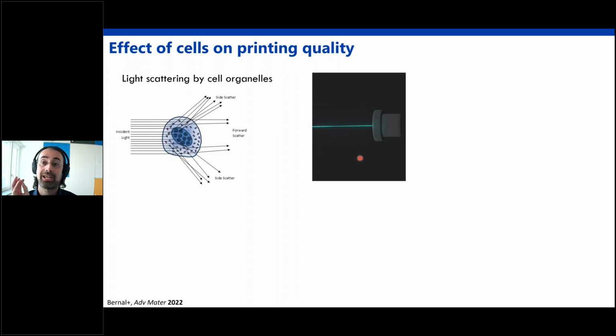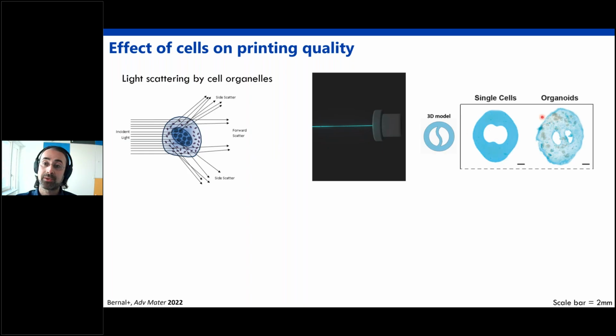And the technology relies on delivering light in a very precise manner in 3D. And unfortunately, or fortunately, actually, cells are scattering elements, so they scatter light. I say fortunately because that makes possible the use of flow cytometry as a characterization method. But of course, for printing, this is potentially a hurdle. So if you try to print either single cells or liver organoids, even already inside this sort of yin-yang structure, you get a very poor approximation of what the object should really be.